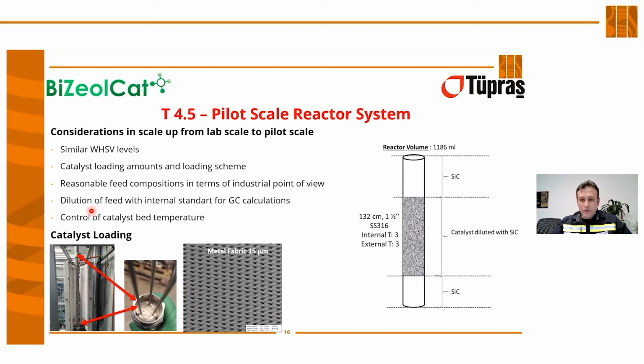We load the catalyst diluted with silicon carbide right in the middle of the reactor tube, and we control the reactor externally, measuring the reactor temperatures internally from three different locations. We are very good at controlling the catalyst bed temperature, but the external temperatures are almost 50-60 degrees higher than the internal temperatures because of the endothermic nature of the reaction.